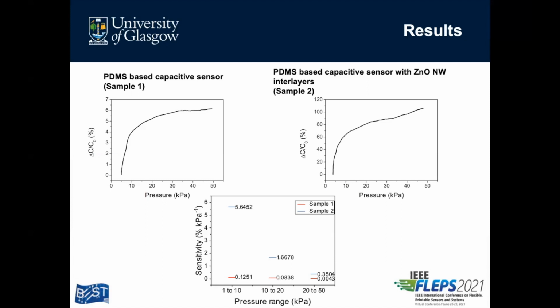The sample with zinc oxide nanowire interlayers showed a higher sensitivity for all pressure ranges, especially at the low range from 1 to 10 kilopascal, with an improvement of about 50 times higher than the standard PDMS sample. So the addition of zinc oxide nanowire layers has clearly played an important role to improve the sensitivity. And this enhancement in sensing performance is attributed to the piezoelectric effects of the zinc oxide nanowire interlayers.